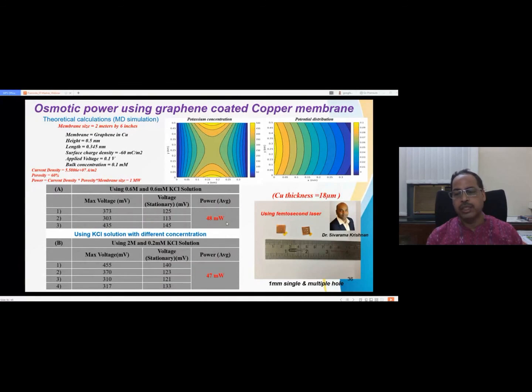we have to make the hole. Instead of making a nanohole, there are two aspects. If you decrease the thickness of this membrane, because we are already working with the 2D material, you get a higher current, and also if you increase the size of the pore, you also get a higher current. Then you can get more power. If you reduce the size of the pore, you can get a higher voltage, but the current becomes higher if the pore size becomes larger.